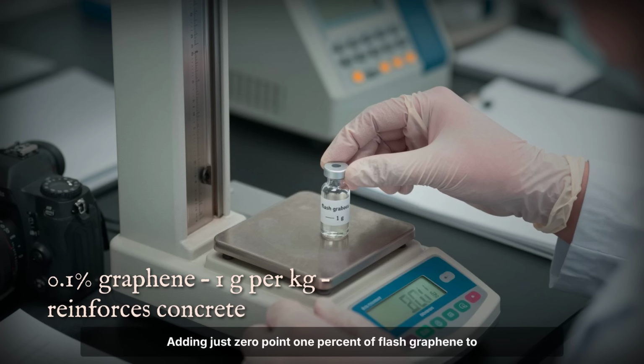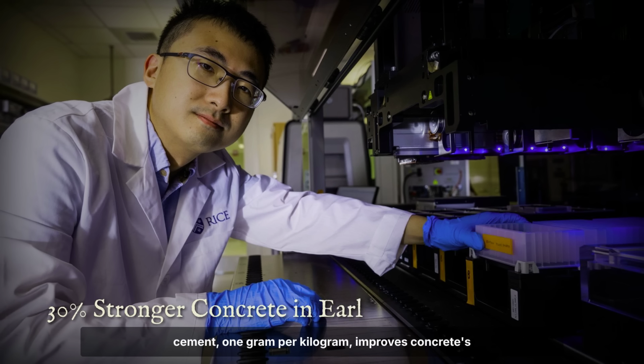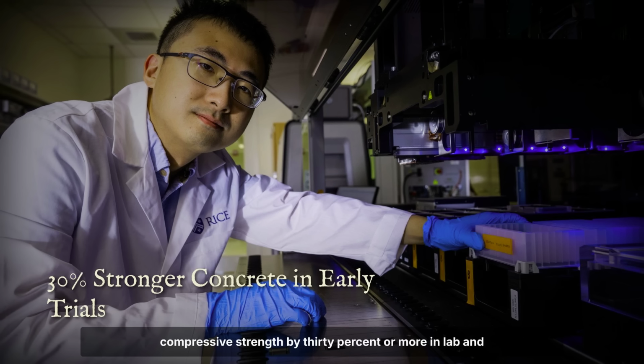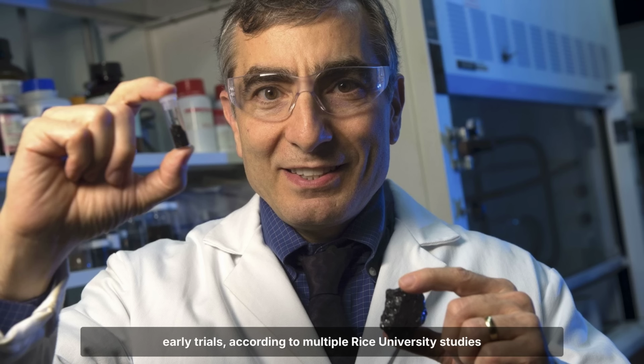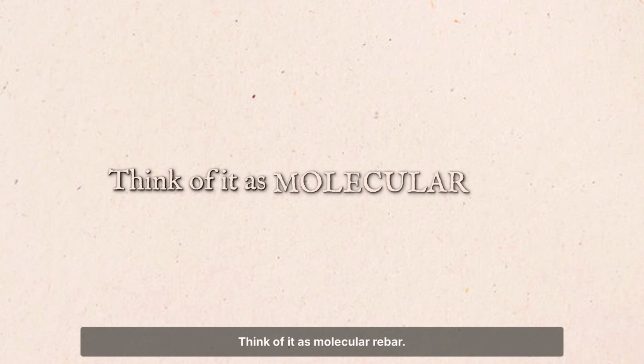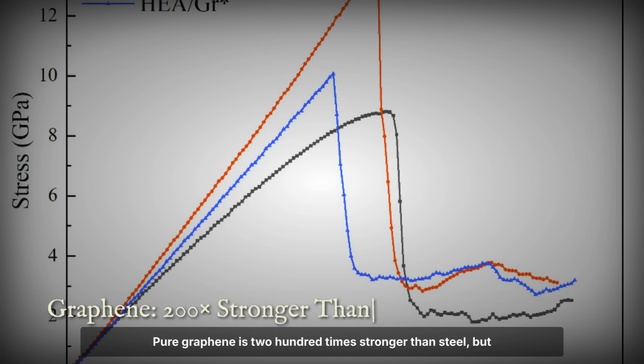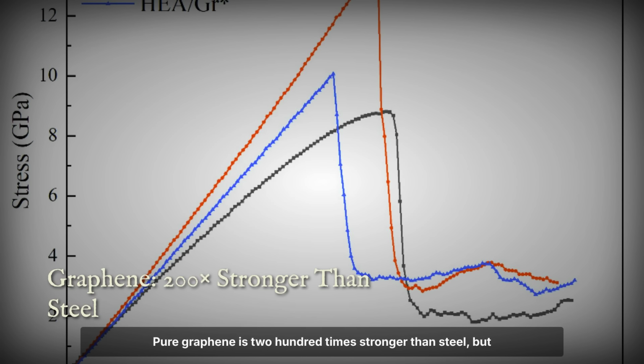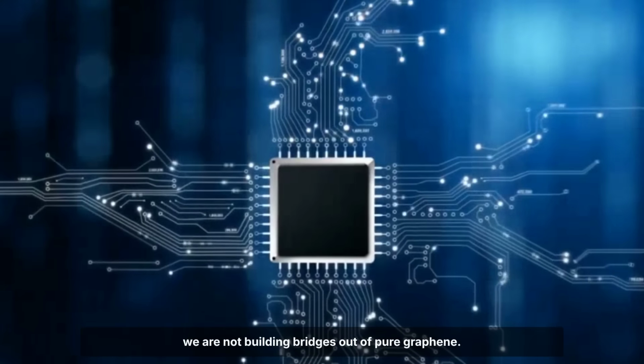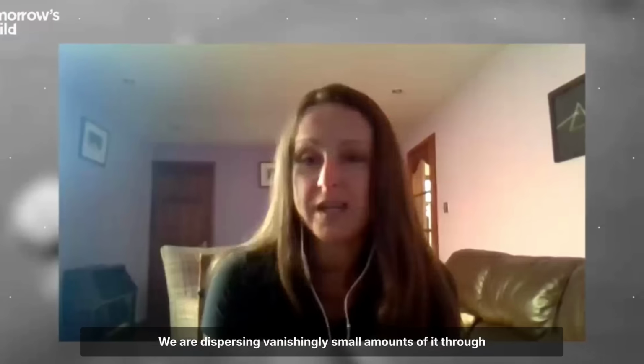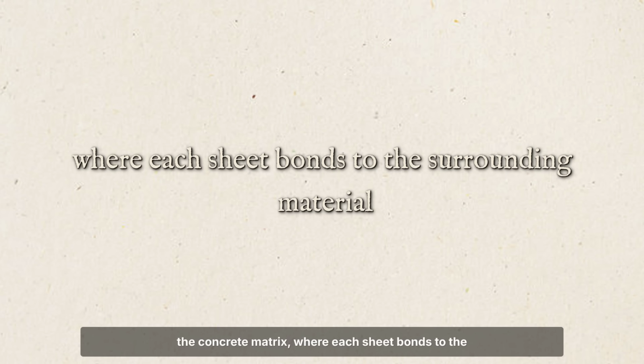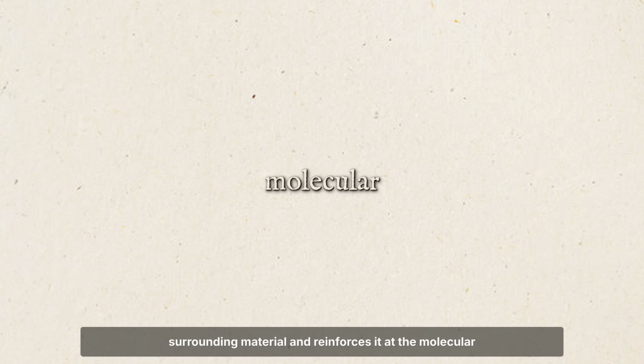Adding just 0.1% of flash graphene to cement, 1 gram per kilogram, improves concrete's compressive strength by 30% or more in lab and early trials, according to multiple Rice University studies published since 2020. Think of it as molecular rebar. Pure graphene is 200 times stronger than steel, but we are not building bridges out of pure graphene. We are dispersing vanishingly small amounts of it through the concrete matrix, where each sheet bonds to the surrounding material and reinforces it at the molecular level.